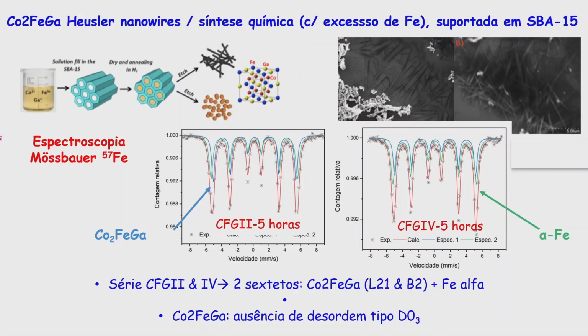But using what you have in the literature, by using the chemical route, supported by SBA-15 silica, mesoporous silica. This is the way: you use this structure to get nanowires, and then you get rid of the silica by dissolving the silica chemically, and you get your material. And people say that this works. You get pure cobalt-2 iron gallium, and you apply this recipe, and we see that you have a lot of iron together. And why do people say that?